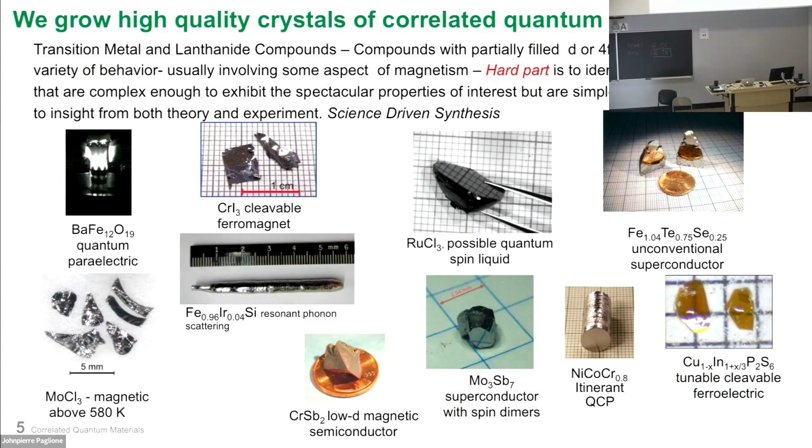So this is grown at an oxygen pressure above 60 bars of oxygen gas. The system we have goes up to about 100 bars. So this is essentially the pressure in an oxygen gas cylinder. We can apply that pressure while we're growing by the floating zone technique.